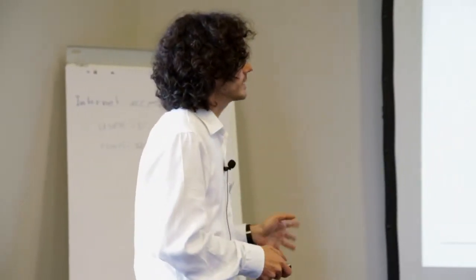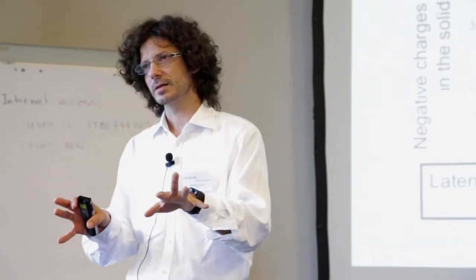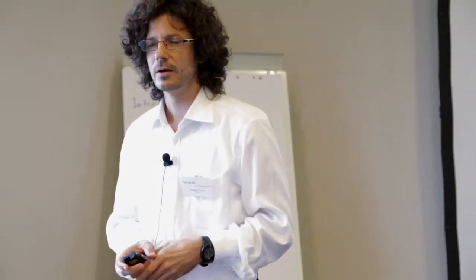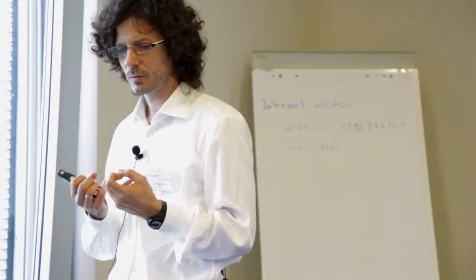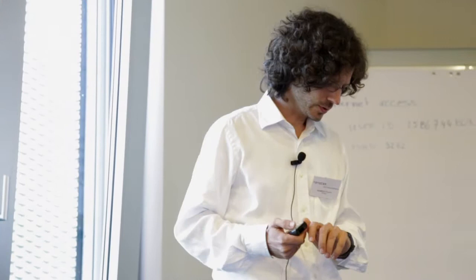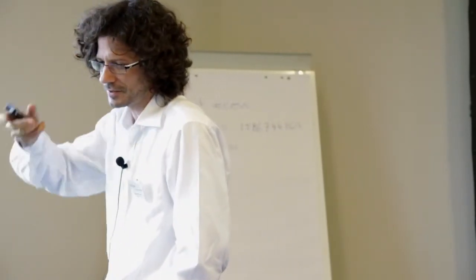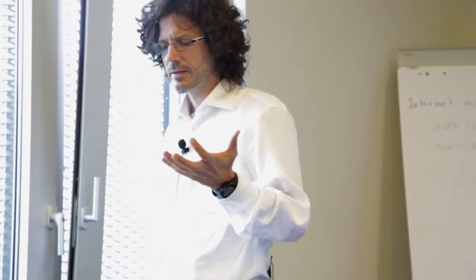The question is, do we suddenly release more polymer after a certain time and the material becomes more fluid, for example? Or do we have one phase which gets lost by creating a lot of these platelets, but it's stable, so it's not creating a perturbation? So I think these are questions that are still worth thinking about. And this morning I was scratching my head about how to present this, and it dawned on me that, actually, it's something I had in mind for a fair amount of time, that the notion of competitive adsorption with other ions such as sulfates, which is known to perturb the action of superplasticizers, should in principle be roughly at stake also here.